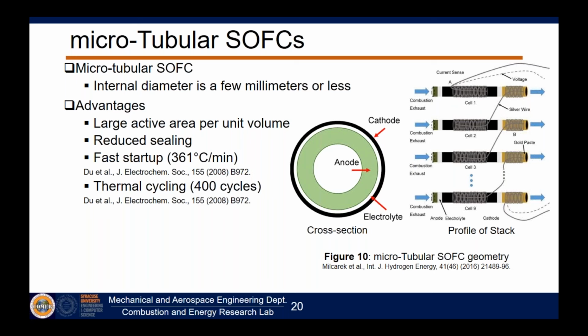Why did we switch to these tubes? Because they're a lot easier to seal. Remember I said the sealing was part of the issue with the dual chamber. Well, these are a little bit easier to seal, and we found over time with a lot of research that you can generally heat these things up a lot faster, and we can also thermal cycle them. Up to 400 cycles at least has been done, and 361 degrees Celsius per minute is a whole lot better than 5C per minute, right? So these are the microtubular solid oxide fuel cells.